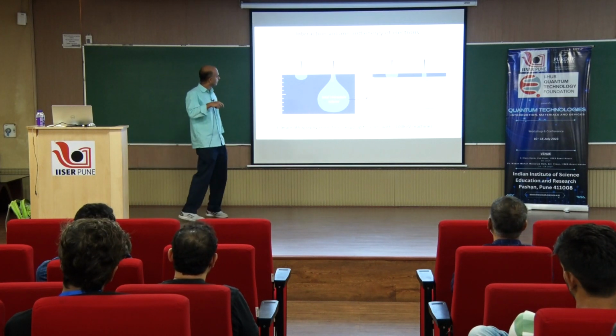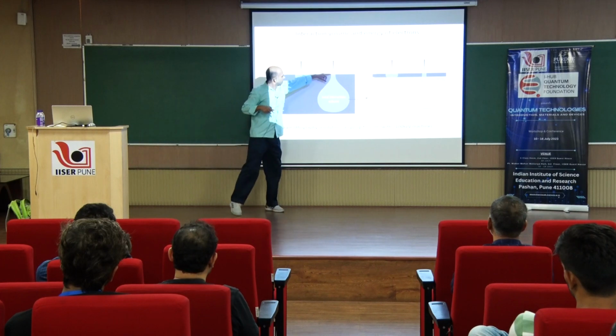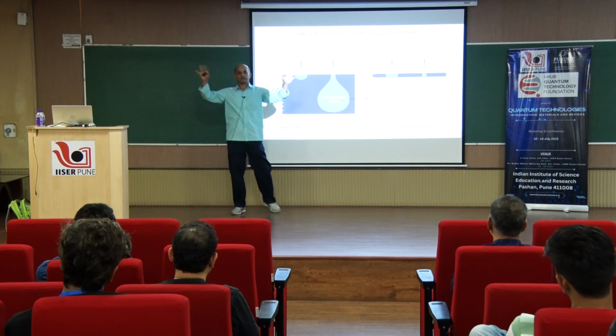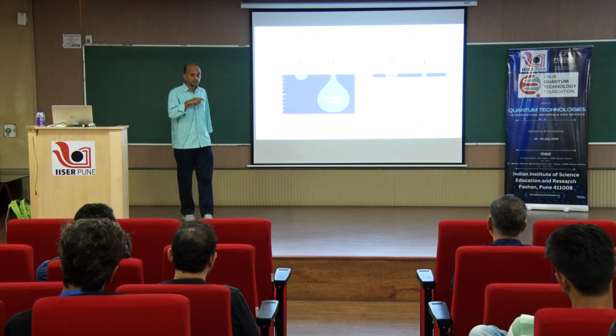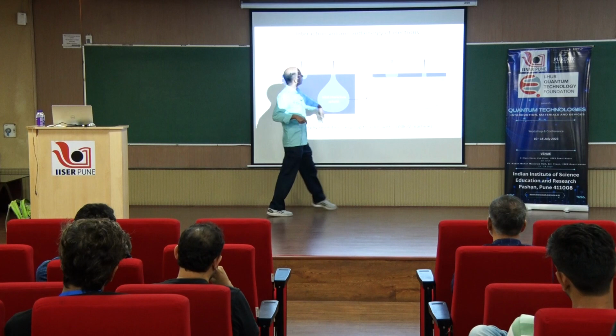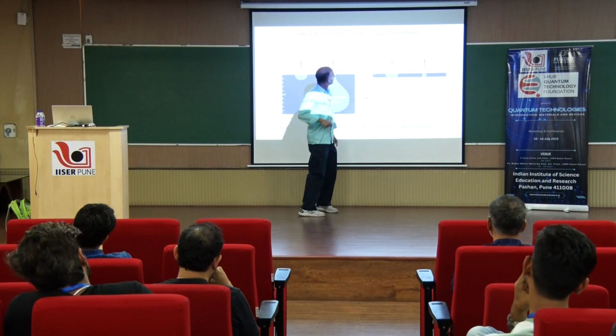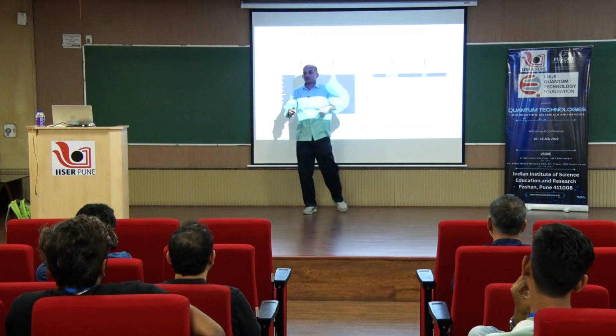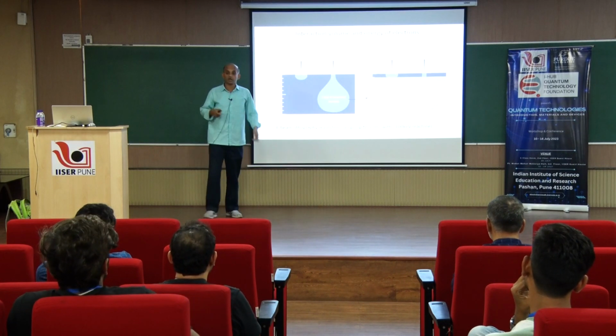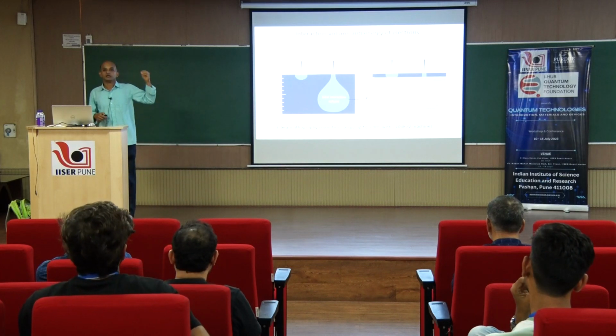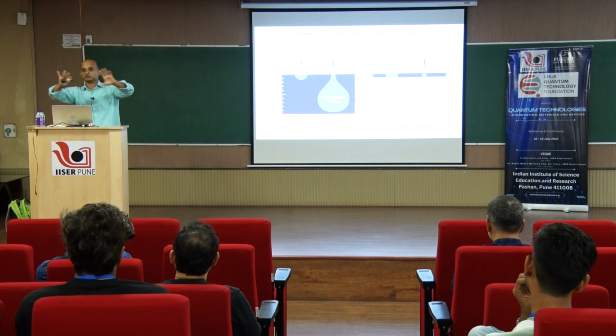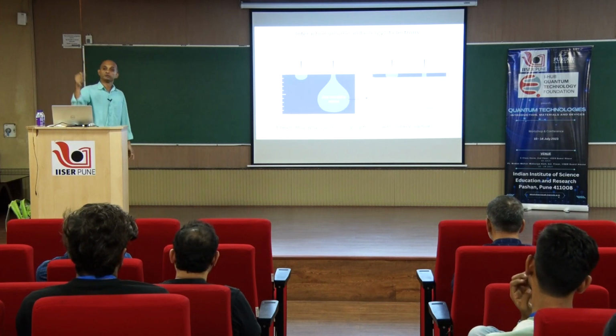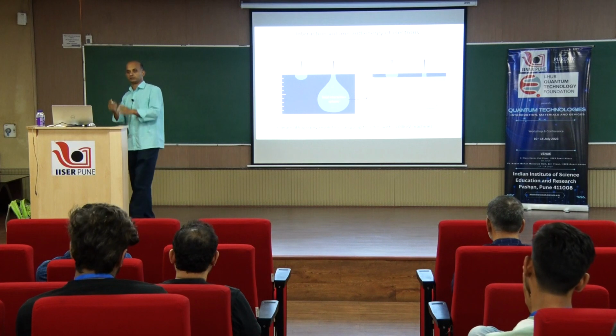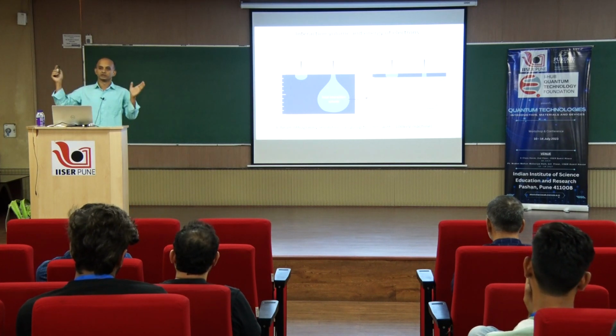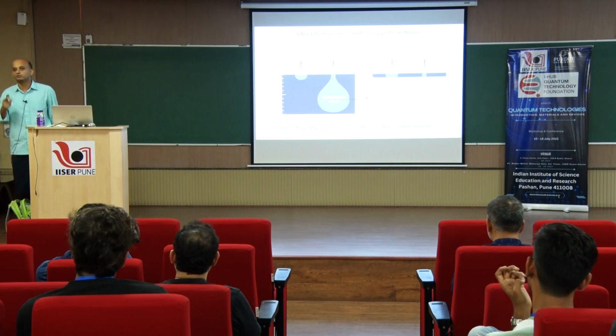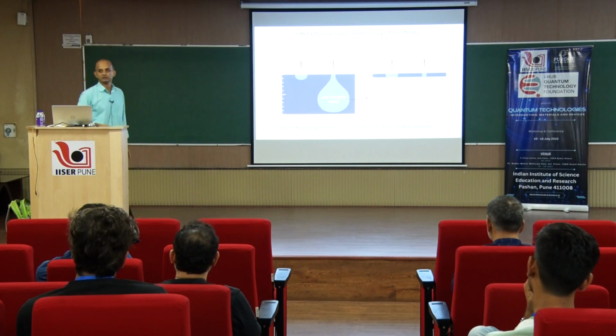If you are shooting at a very high kV, the interaction volume on the surface is very small. Deep inside it will expand, but we generally coat a very thin layer of resist, so we do not see this part; all we get is only this neck part. At 5 kV your interaction area is larger, so if you want to write, say, a 200 nanometer pattern at lower kV, you use a lower dose because the spread is much higher there. At higher kV you have to use a higher dose, and you will get a finer pattern, finer features. So if you get stuck and cannot make finer features, the first thing that should come to your mind is to do it at the highest kV available.